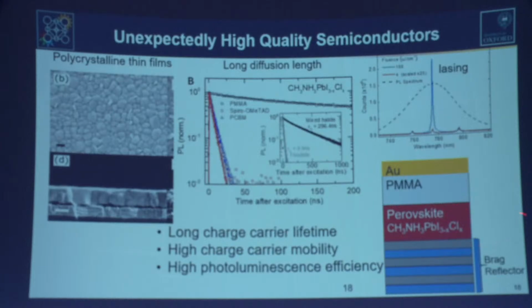This exemplifies one of the things people try to do with really good quality semiconductors: see if you can get lasing from them. For lasing to occur, light amplified spontaneous emission, you need to populate the electrons in the conduction band, and you have something called population inversion, where you get such a high density that suddenly you get spontaneous emission. That happens with these simply processed perovskites. If we just put them in an optical cavity, basically between two mirrors, you get this lasing line, characteristic of a very narrow line emission. So that was a surprise.